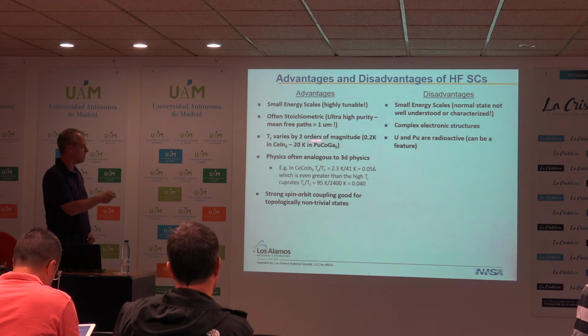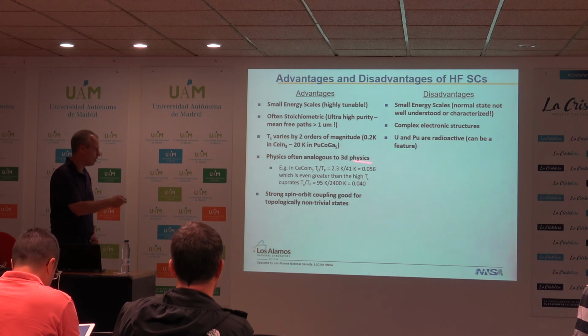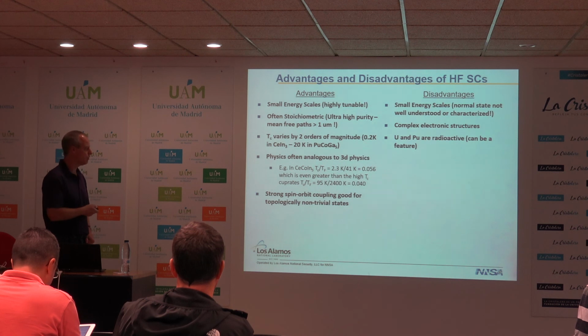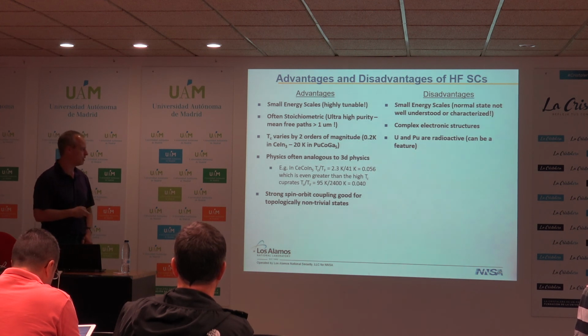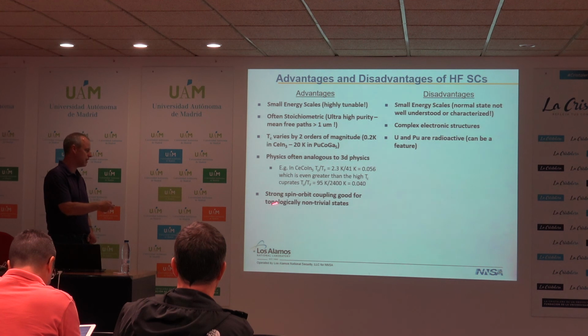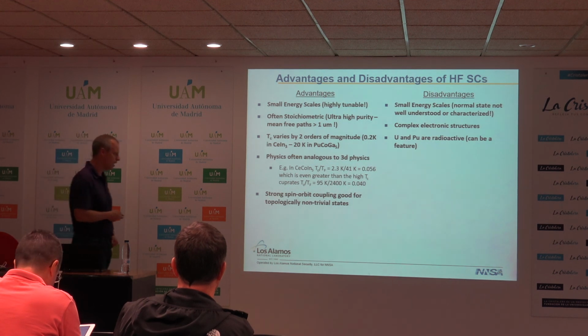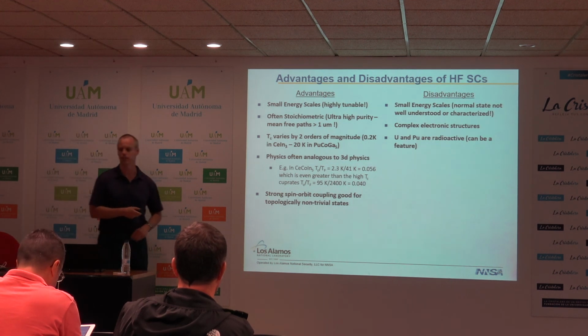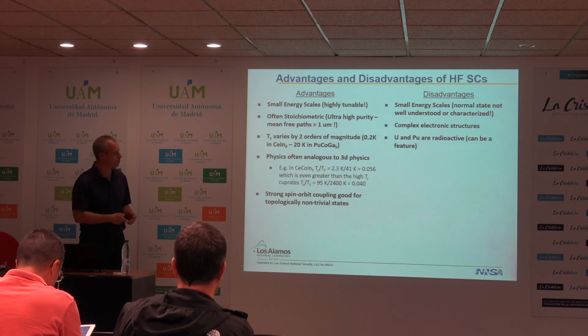I already emphasized this, the family of 115 materials, with Tc varying by 2 orders of magnitude. One of the big take-home messages is that the physics is often analogous to the physics that we see in 3d systems. You know, Tc over the Fermi energy in cerium cobalt indium 5, again 0.05, is comparable with what you see in cuprates. And finally, I think an interesting direction will be to look for topological superconductivity in these systems. Sometimes you deal with uranium and plutonium.